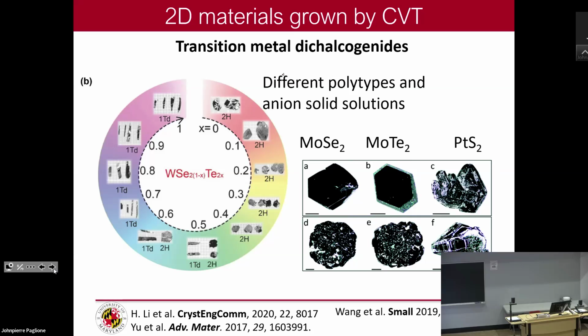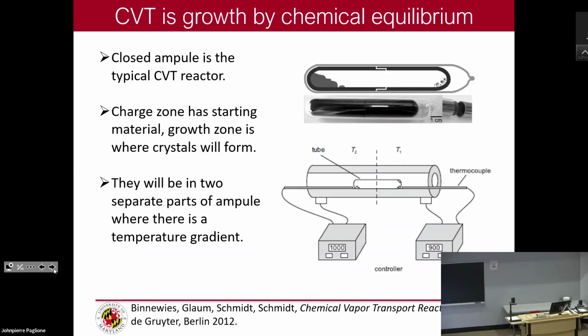These are transition metal dichalcogenides, and in my lab, we've been doing the thiophosphates, selenophosphates, and also the metal dichalcogenides like niobium diselenide recently. So one thing about CVT and transport is that indeed you want some kind of horizontal tube that goes into a horizontal furnace, and that you want to have at least 2 zones so that you can put a temperature gradient on it. And then you need to think about the charge zone, which is going to have your starting material, and then your growth zone where your crystals are going to nucleate and then grow.